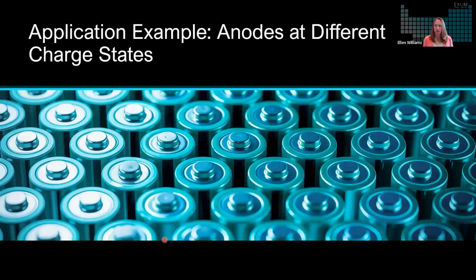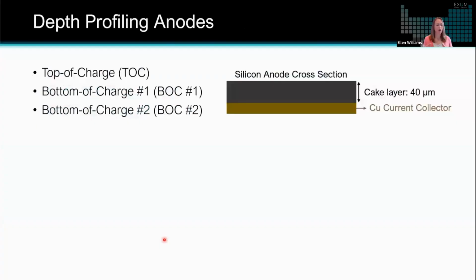So we'll now move on to our second application example, where we're looking at anodes at different charge states. So this is an example of, as you've developed a new silicon anode or a new battery chemistry, you're working on your cell geometry optimization, starting to increase the pilot line capabilities and process control. You can evaluate how your lithium is migrating between top and bottom of charge in these silicon anodes, and potentially optimize your formation cycling process as you're standing up this new cell geometry